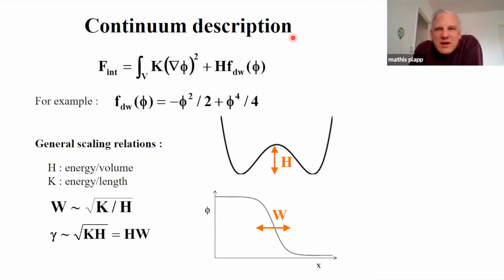In the continuum description, you start from a free energy functional. So your free energy, the total free energy of your interface, is a volume integral over an integrand that has two terms. That is one. The second one here is a double well potential, which has this shape here. It's a double well potential for the order parameter, and the two minima precisely give you the constant values of this order parameter that correspond to the two phases. And the first term is a gradient square term. This arises from the interaction between the different parts of the system and is always there as soon as you have interactions.